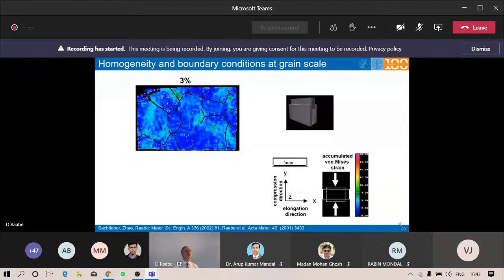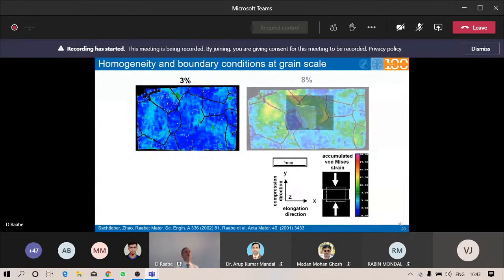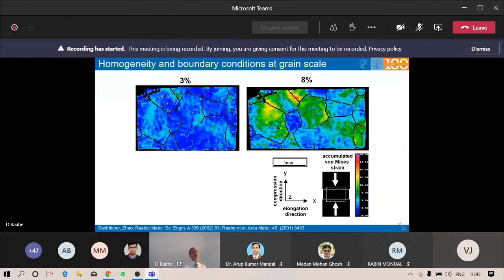And when you then measure the deformation of these, this is the experiment shown in color code now, you see that just from the variation of the orientation, you get an enormous inhomogeneity of this deformation pattern. You see the little blue grain in the center was practically not deformed. When you even have 15% total thickness reduction of that columnar polycrystal, you see that some of the grains